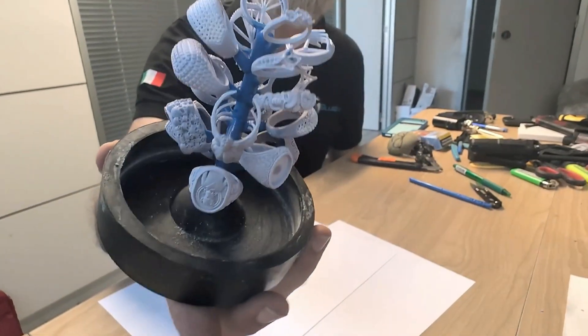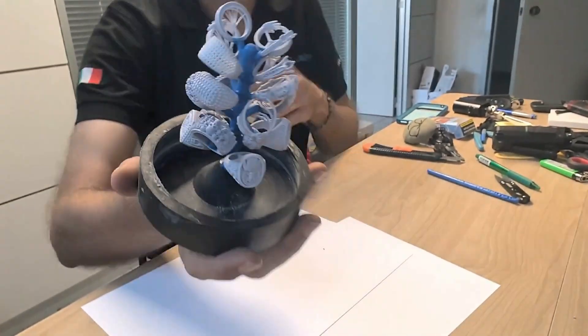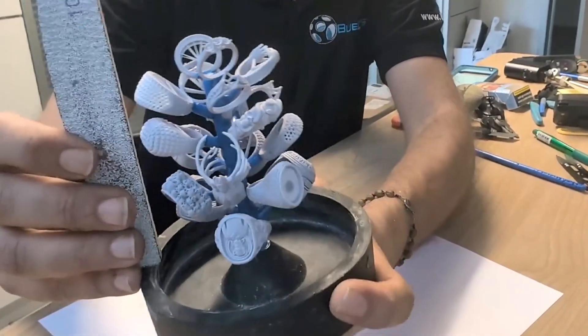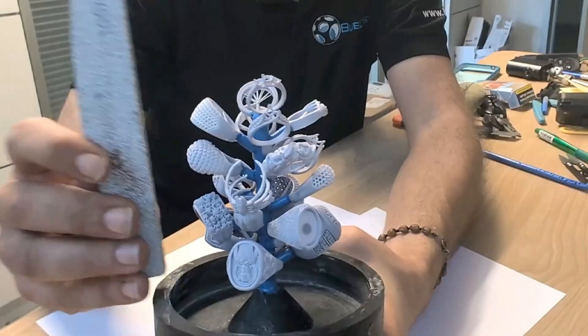Here is the final result that we will be casting in the next few days. As you can see the models are all at least 3mm apart from each other and have a minimum distance of 5mm from the edge of the flask.